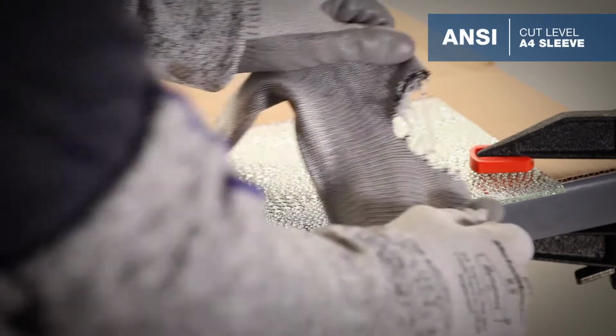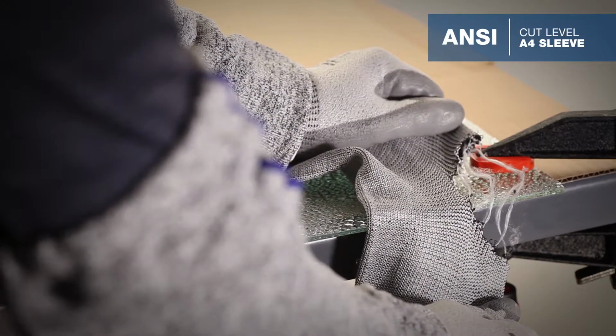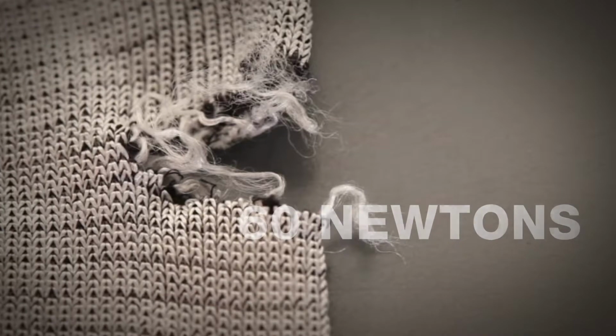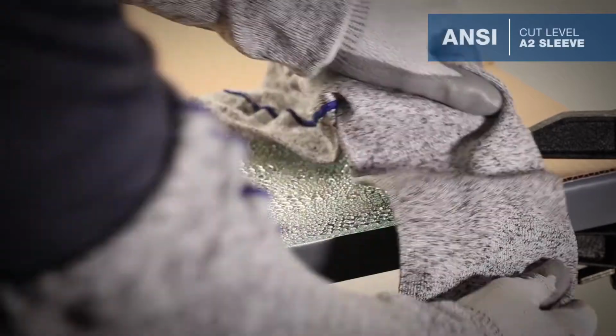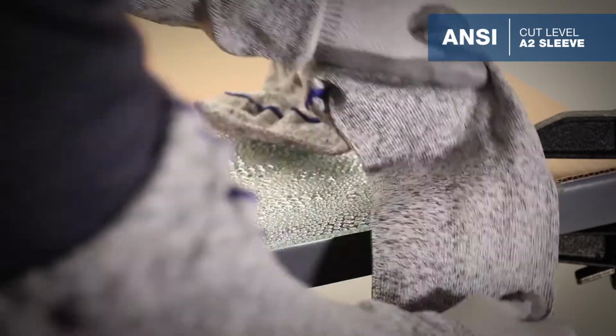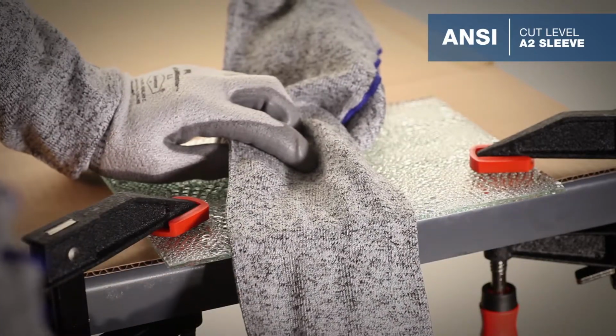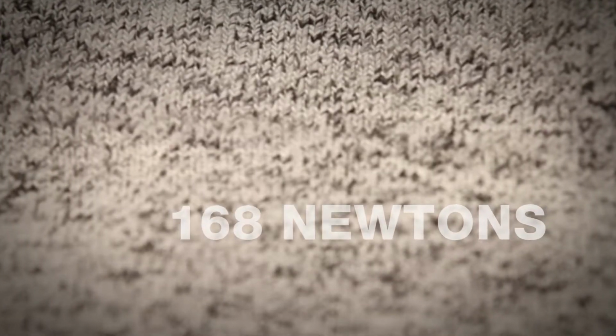This is an ANSI cut level A4 sleeve. One pass, it fails. Why? Because the yarn in this sleeve had only 60 newtons in tensile strength. This is an ANSI cut level A2 sleeve. After multiple passes on the same crock glass edge, there is no cut through. This sleeve was knitted with Dynamax HD yarn, which has a single-strand tensile strength of 168 newtons.